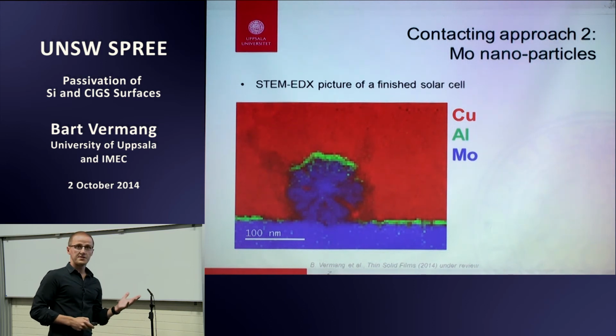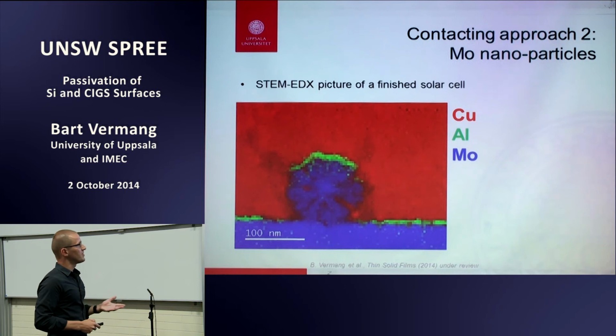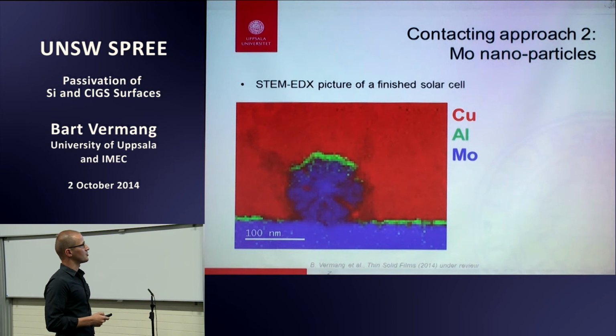It's also being used as a reflector, so you can optimize the reflection a bit more. We have not been using it yet, so they're still quite large. These are nanoparticles of 100, 150 nanometers, so plasmonics or whatever we have not been doing yet. But it might be even an opportunity to get some plasmonic effects inside the CIGS absorber layer.